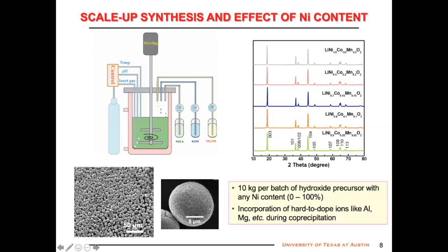So all the samples I'm going to present data on were made by co-precipitation of the hydroxides and firing with lithium hydroxide. We can actually make any composition, 10 kilogram of hydroxide precursor per batch, nickel content anywhere from 0 to 100%. We can also incorporate hard-to-incorporate dopant ions like magnesium and aluminum during the co-precipitation. So all the data I'm going to show you, they have secondary particles of 10 to 12 micron. And primary particles, one secondary particle is shown here, so you can see how the primary particles are sticking together. And they also get good, nice crystalline faces.